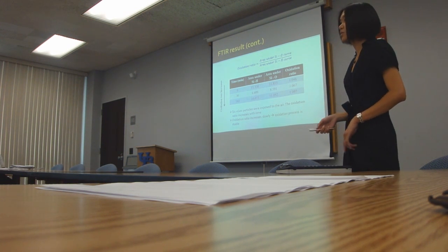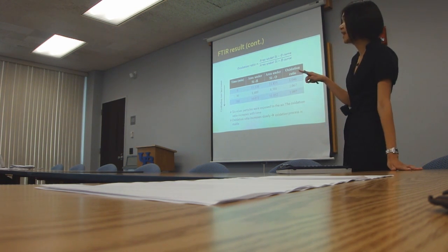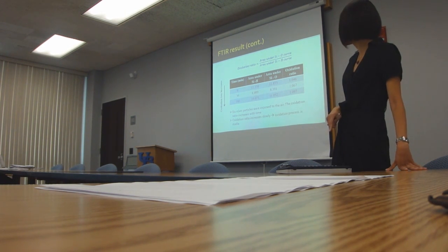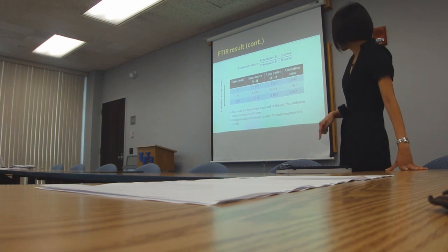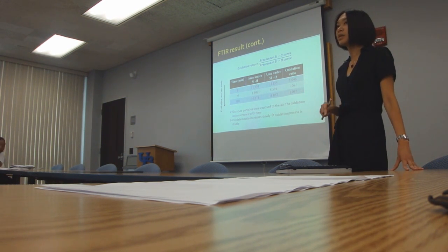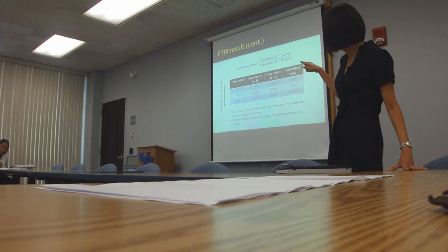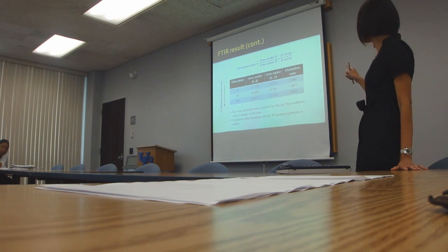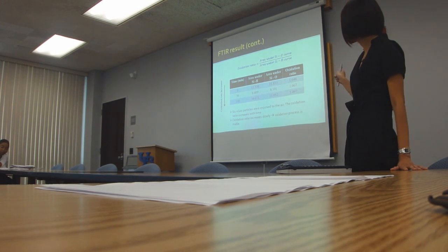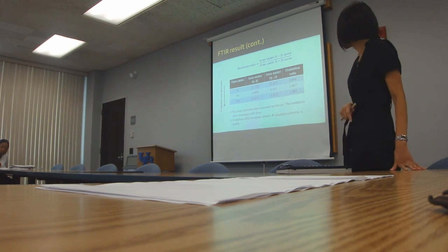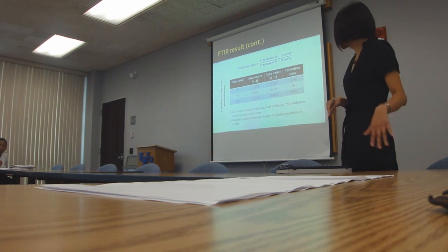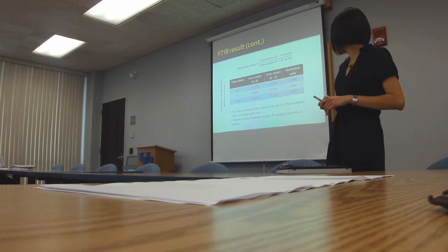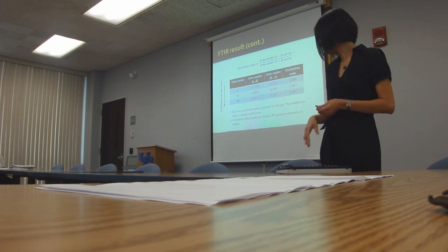The oxidation ratio is calculated by dividing the area under the Si-O curve by the area under the Si-H curve. We expect the oxidation ratio to increase with time. This trend is shown here. The oxidation ratio increased from 1.046 to 1.097 from 0 minutes to 180 minutes. Also, the oxidation ratio increased slowly, which indicates that the process is quite stable.